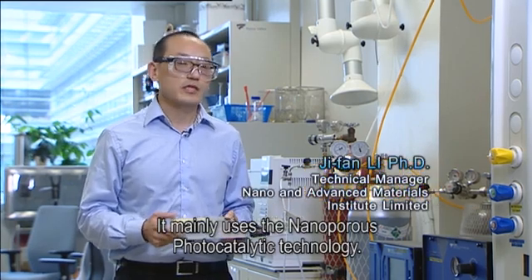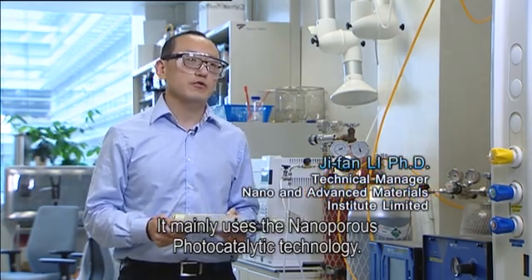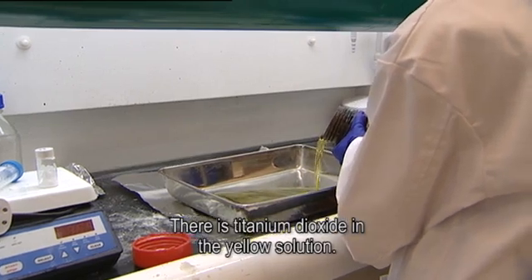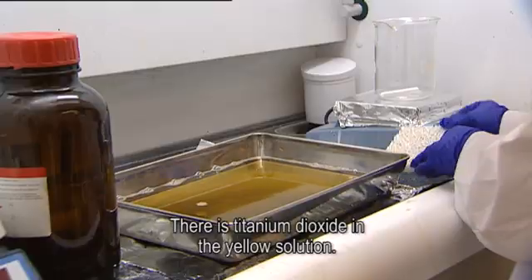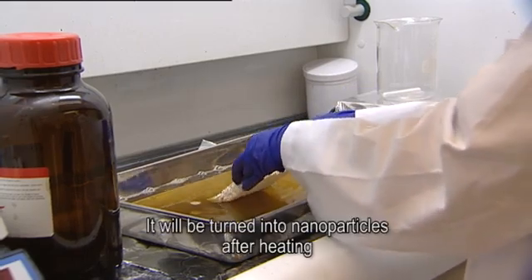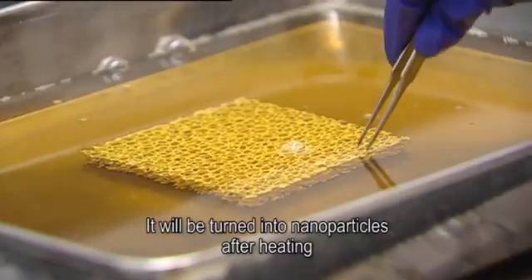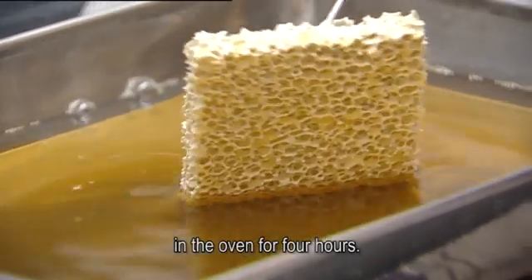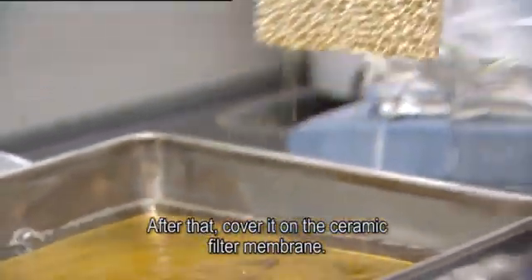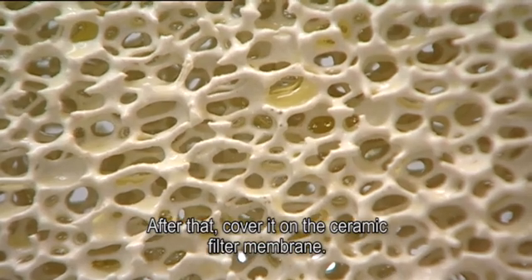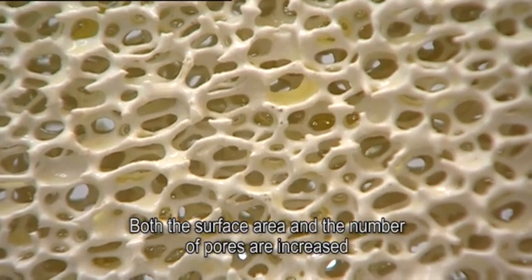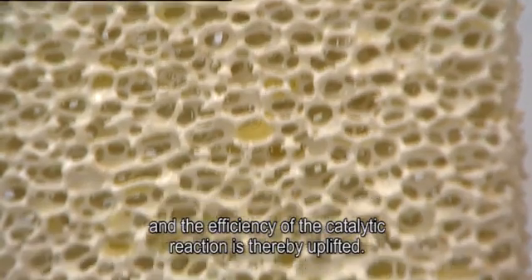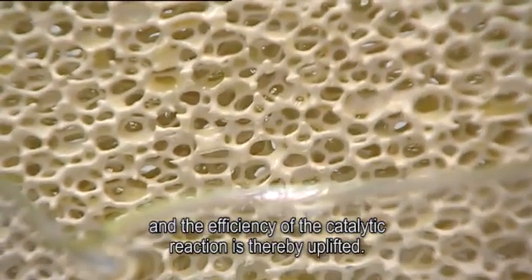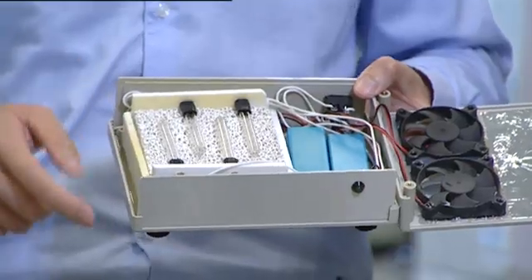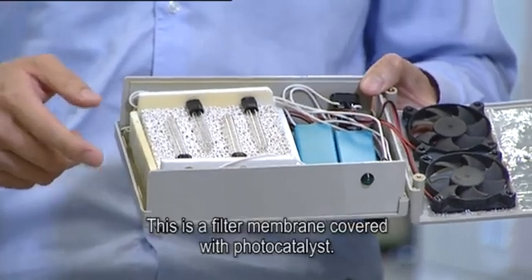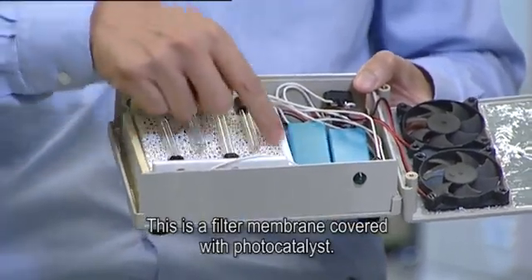It mainly uses the nanoporous photocatalytic technology. There is titanium dioxide in the yellow solution. It will be turned into nanoparticles after heating in the oven for 4 hours. After that, cover it on the ceramic filter membrane. Both the surface area and the number of pores are increased, and the efficiency of the catalytic reaction is thereby uplifted. This is a filter membrane covered with photocatalyst.